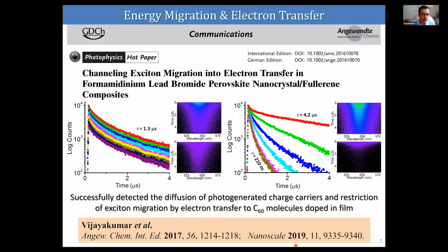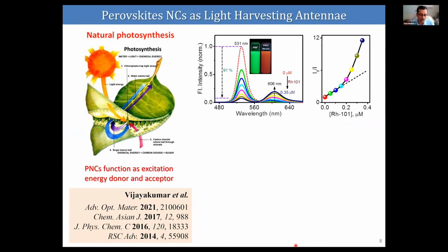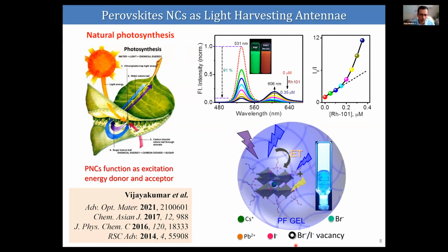And these materials are showing efficient excitation energy migration and electron transfer, just like natural photosynthetic systems. So we tried to understand the excitation energy transfer in this material to suitable donors, so energy transfer, and how these materials can act as light harvesting antennas. And we found that they show very good light harvesting antenna properties, and they can nearly completely transfer the excitation energy to suitable dye molecules, and show the superquenching phenomenon. And not only that, they can act both as energy donors as well as energy acceptors.